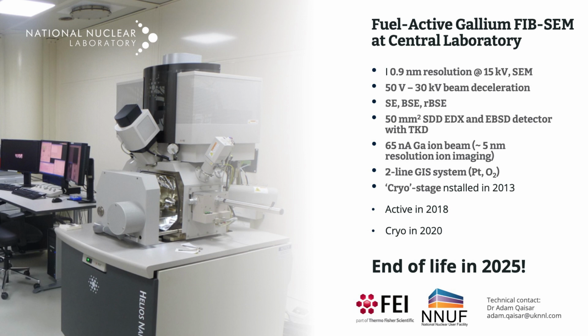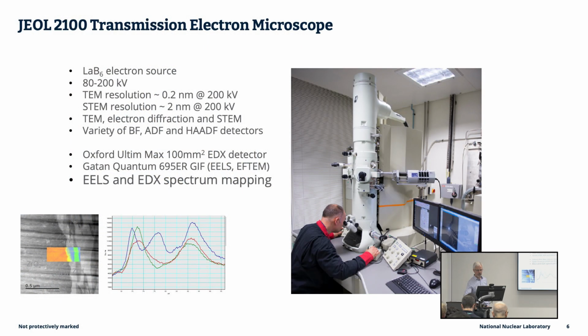Jack showed before an image that was polluted by curtaining artifacts from the sample thinning. When I say cryo, it's not really true cryo. About -100 is good enough, and we're going to be carrying out some experiments during this year to find out whether even -100 is overkill, whether we can get away with not chilling things that far. Depressingly, from a facilities point of view, the manufacturer have told us they're not going to be offering service contracts beyond 2025 on this instrument, which is really quite disappointing, but by the by.